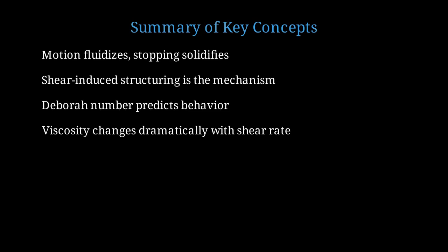Let me summarize the key concepts we've covered in this lesson. The fundamental principle: motion keeps materials fluid by preventing structure formation, while stopping allows solidification. The mechanism is shear-induced structuring. Shear disrupts molecular networks during flow, but allows them to form when flow stops. The Deborah number, comparing relaxation time to process time, predicts whether a material will behave as liquid or solid. For shear thinning materials, viscosity can change by orders of magnitude as shear rate varies. This phenomenon has critical applications in bioprinting, drug delivery, food processing, and industrial manufacturing.